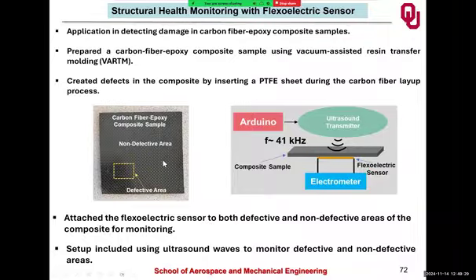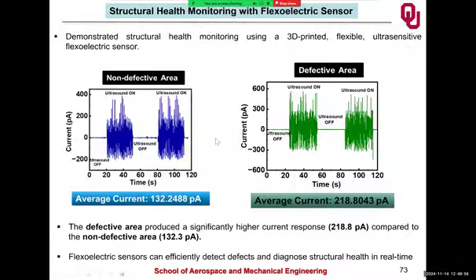This is the carbon fiber epoxy based composite sample. What we did was make a defect intentionally for this characterization inside the composite material. This is the defective area and this is the non-defective area. We placed our sensor over the defective area as well as the non-defective area, and we used the ultrasound transmitter and got the signal.